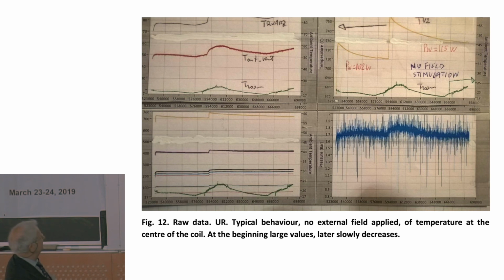Again high temperature, but later it goes down again. This is a typical experiment, we were not able to avoid this, we call it self-quenching. It tends to go to a minimum. If we wait 3-4 days, the value goes close to zero. So we need to change something.